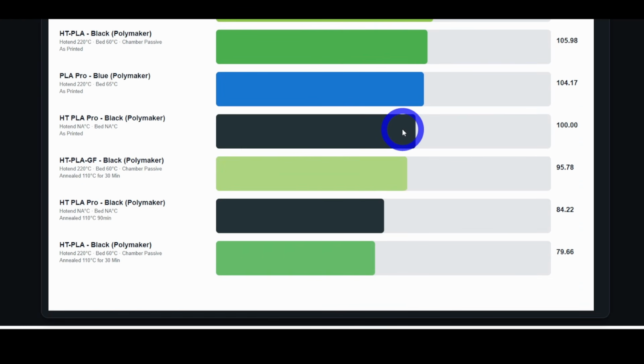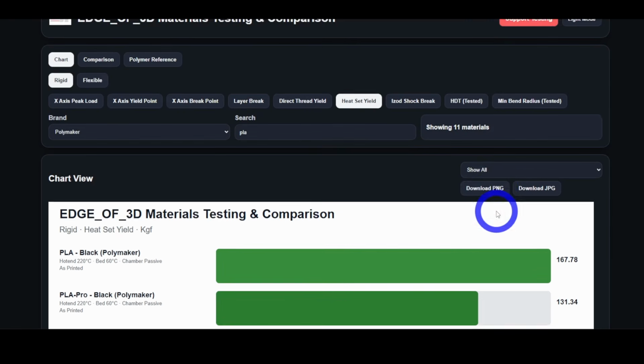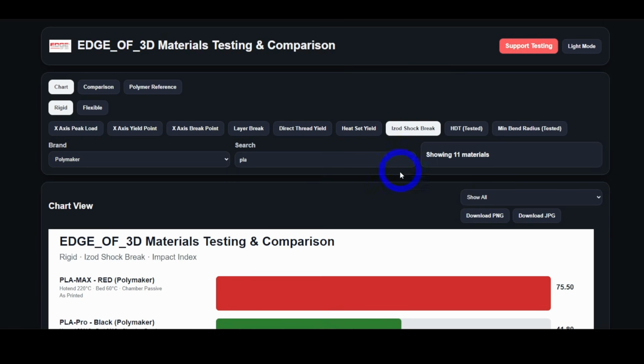And here's where we are. As printed, 100 kilograms of force. Annealed, only 84 kilograms, but both of those are significantly better than the direct thread, so this will benefit from having heat sets. Izod shock test.